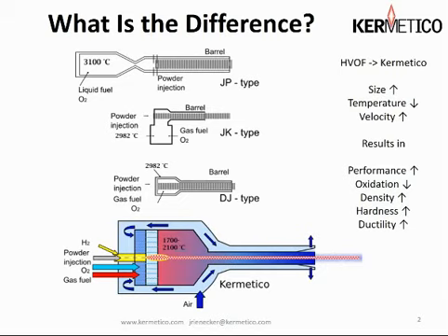Fuel and air come into the combustion chamber either with or without oxygen, depending on what we're spraying. And that air is preheated by having cooled the combustion chamber first, so we're making maximum use of that heated air. The transition to the nozzle is smooth, and the nozzle can be as long as it needs to be to achieve the desired velocity, which could be as high as the gas velocity.